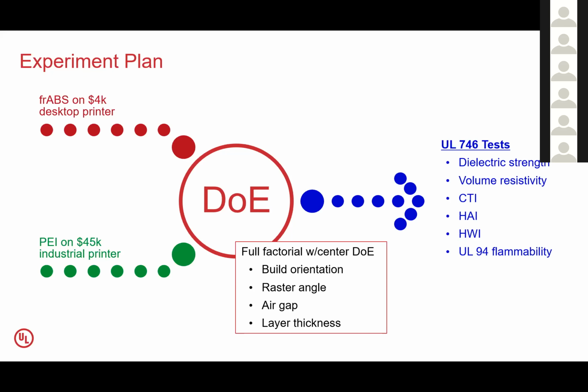We looked at a full factorial with the centered design of an experiment, and to look at these different factors. But we took it one step further, where we took our filament and we sent it to our lab, chopped it into pellets, and then injection molded those pellets. So now we've got injection molded material that was made from the same feedstock as our 3D printed filament parts. And then we looked at a number of different electrical ignition flammability properties: dielectric strength, volume resistivity, comparative tracking index, high current arc ignition, hot wire ignition, and UL94 flammability.